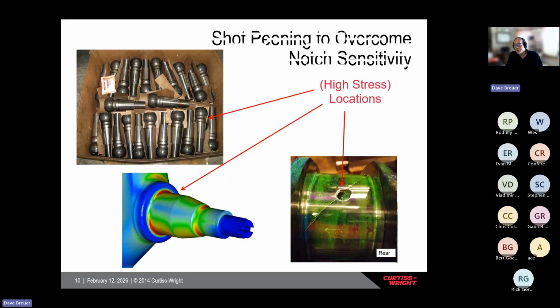Okay, so everything we shot peen, almost everything we have has some type of geometric or metallurgical stress riser. So in these ball studs, this radius underneath the head here acts as the high stress area. This is a large engine crankshaft. You can see a fatigue crack going from this, starting in this web, going across the oil hole to this web. I don't know where the fatigue crack started, but the stress risers are going to be this radius and this oil hole, and of course you can see the crack going right through all of them.